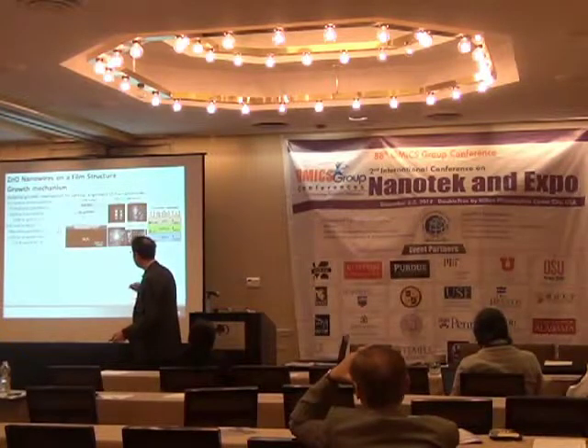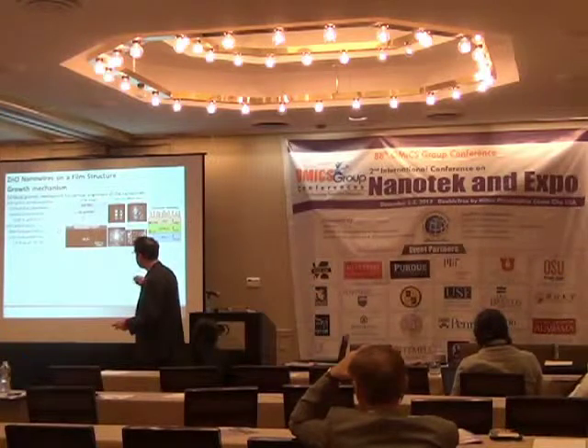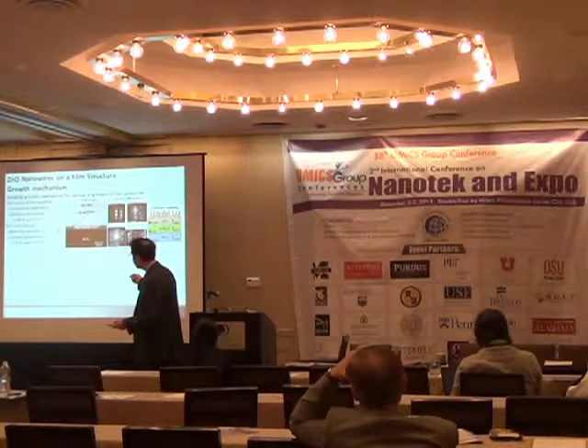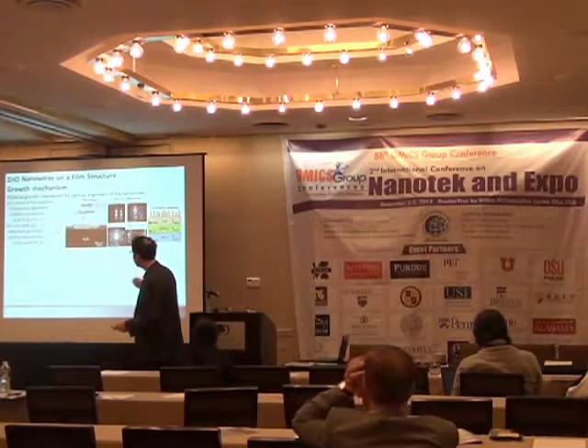So now, before looking at the result, let me very briefly explain the reason why we have a good single crystal. We grow the material at very high temperature, and for that reason, we form an intermediate layer between the substrate and the zinc oxide, and that intermediate layer is a spinel phase that enables reduction of stress. So that's the reason we can get a very nice single crystal.